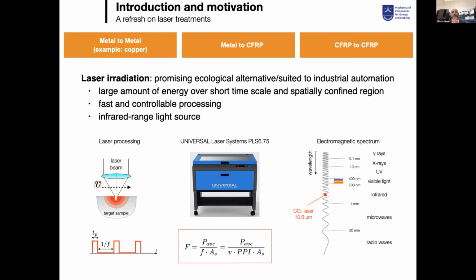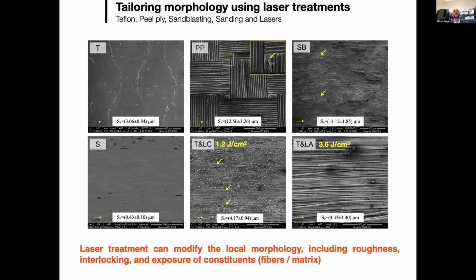The way we do this is by laser treatment. Just a very quick note about this laser treatment. You irradiate the surface with a certain frequency, and the efficiency of your laser treatment depends on what you call the fluence. That is pretty much the quantity of energy per unit surface area that you inject on your surface. And what is important to understand is that depending on the fluence that you are using,